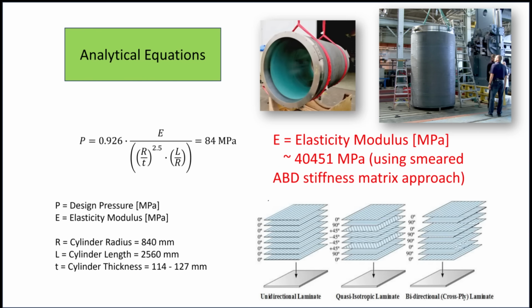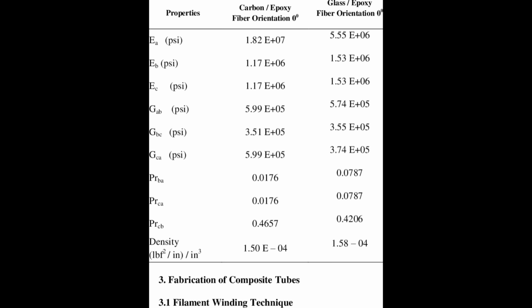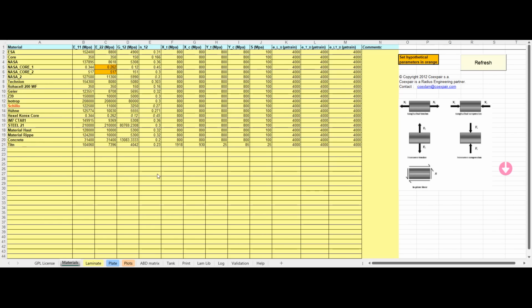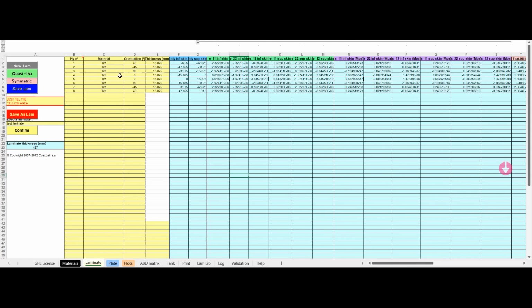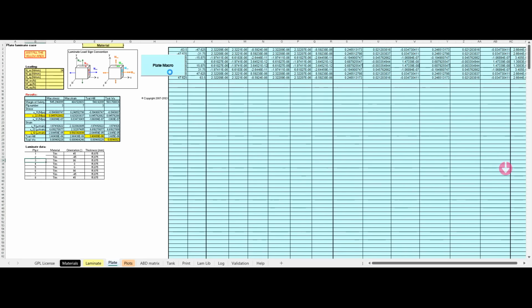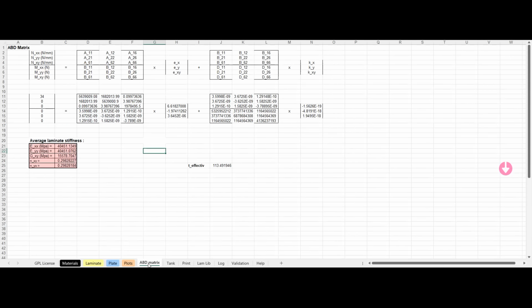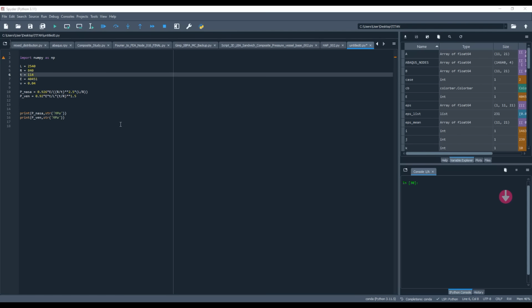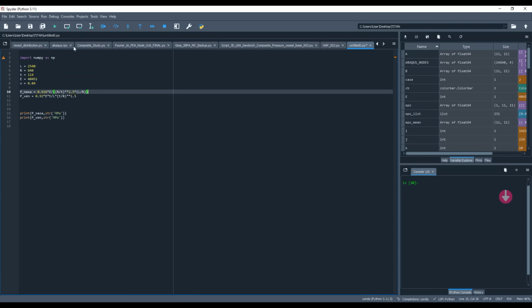The analytical equation shown here is only valid for isotropic material and is not compatible with the CFRP material description, which requires multiple material parameters. But using the well-known ABD stiffness composite matrix, we can treat CFRP as an isotropic material, as we assume the individual laminate layers can be smeared to a quasi-isotropic material. The analytical buckling pressure is estimated to be 84 megapascals using the methodology.